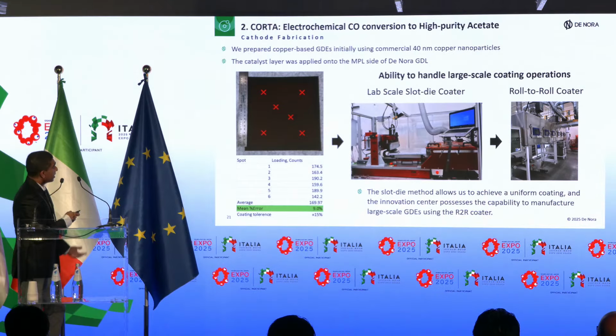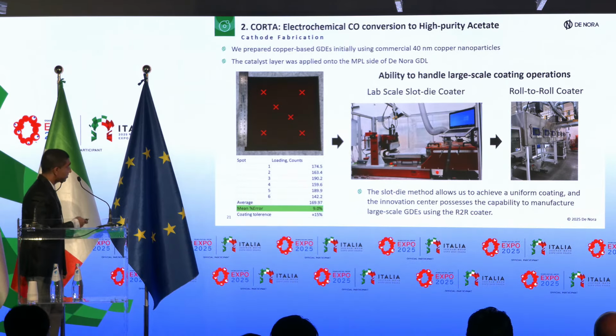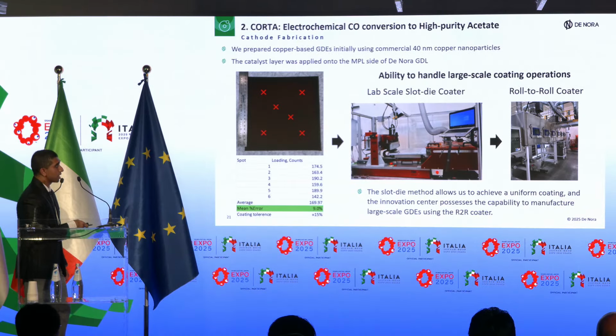So this is the cathode side. Initially, we prepared a copper-based gas diffusion electrode by depositing these copper nanoparticles on our gas diffusion layer, because copper is a good catalyst that can convert carbon monoxide or carbon dioxide into these multi-carbon products. We prepare this electrode using, again, our lab-scale slot die coater, and also note that we have the capability in the future to fabricate this electrode at larger scale in our innovation center using this roll-to-roll coater.